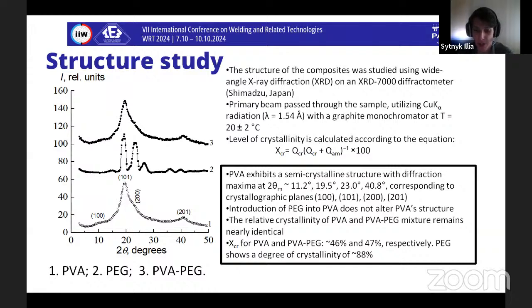This is indicated in particular by the almost identical relative level of crystallinity of PVA and its mixture with PEG, calculated according to the provided equation, where Q crystalline is the area of diffraction maxima that characterize the crystalline structure, and Q crystalline plus Q amorphous is the area of the entire diffractogram in the range of scattering angles in which the amorphous and crystalline structure is manifested. The evaluation of the level of crystallinity shows that PVA and its mixture with PEG have X crystalline values equal to 46 and 47%. It should be noted that the degree of crystallinity of the PEG itself is approximately 88%.